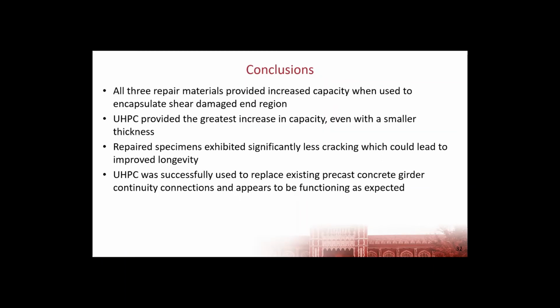So in conclusion, all 3 repair materials that we used provided an increased capacity when used to encapsulate a shear damaged end region, with UHPC providing the greatest increase in capacity, even though it had the smallest repair thickness. Those specimens exhibited less cracking than the initial beams, which could lead to some improved longevity if we encapsulate the ends of some of these beams that have damage.